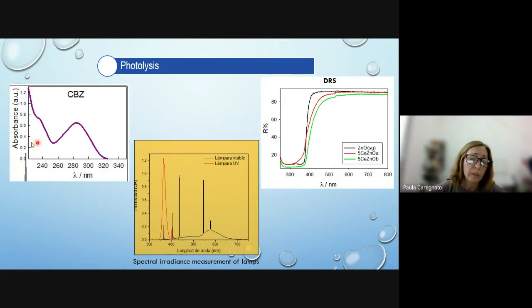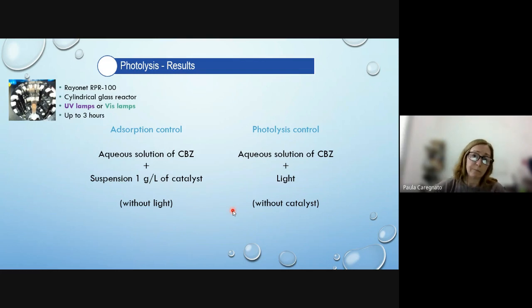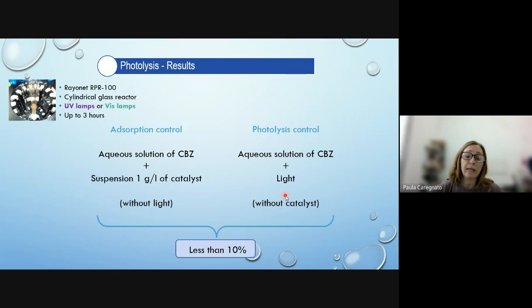Okay, here I'm showing you the absorbance spectra of the contaminant, carbamazepine, and the reflectance spectra of some of the solids, some of the catalysts. As we can see in the spectral irradiance of the lamps, the light was only absorbed by the catalyst. Okay, let's see our results. 2 control experiments were performed, one without light, just the carbamazepine and the catalyst, and the other without the catalyst, just the carbamazepine and the light. After 3 hours of these control experiments, the concentration of carbamazepine decreased less than 10%.